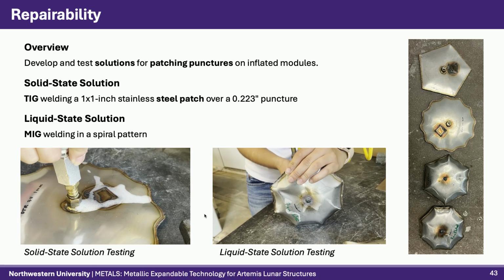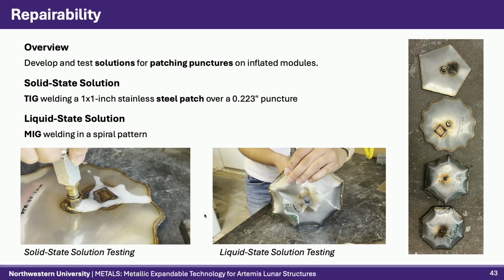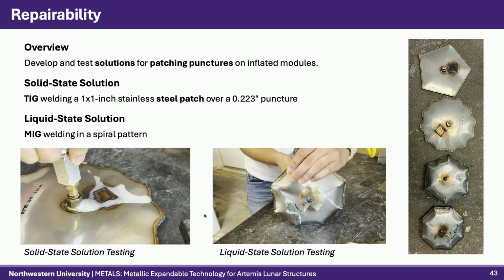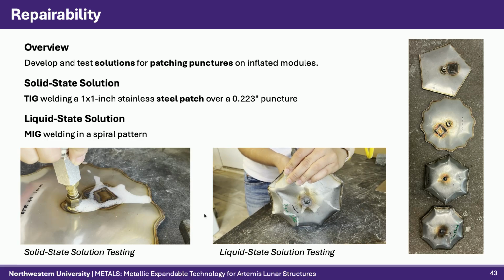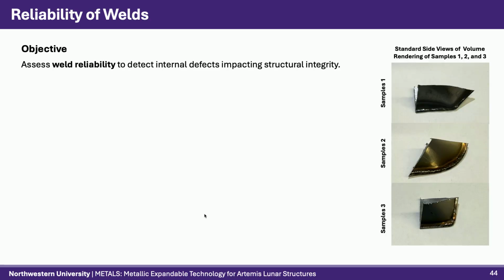Meanwhile, the liquid-state solution applied a filler in a spiral pattern using MIG welding. Compressed air was introduced into both samples, checking for leaks with water and soap. Both solutions effectively sealed the punctured regions with no leaks detected at 55 psi. The solid-state solution is most suitable for larger punctures, while the liquid-state solution is preferable for smaller ones.